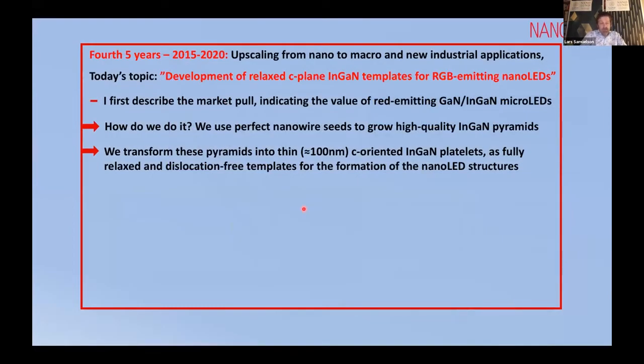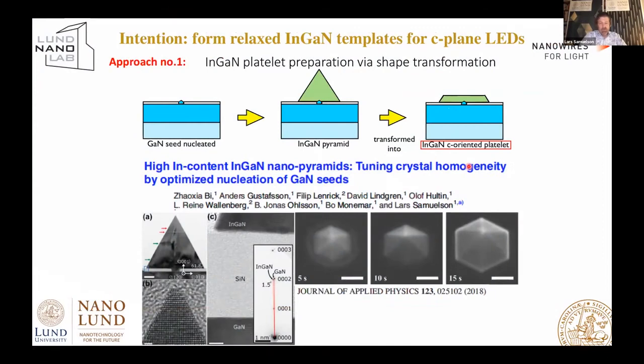Two things I point at in the slides to come here. One is to use perfect nanowire seeds to grow high quality indium gallium nitride pyramids, and then transforming these pyramids into thin, approximately 100, 150 or so nanometer thick platelets of C-oriented indium gallium nitride as fully relaxed, not connected to the substrate, and dislocation-free templates for the formation of the nano LED structures. So here's the first approach.